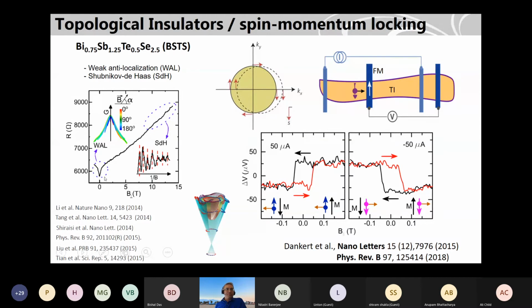For example, this is the magnetic field perpendicular, and this is the resistance. You see a dip here. It's called weak anti-localization, and this appears in materials with high spin orbit coupling. Then you go to a higher field. This is a bit noisy data because it was a very thin flake.